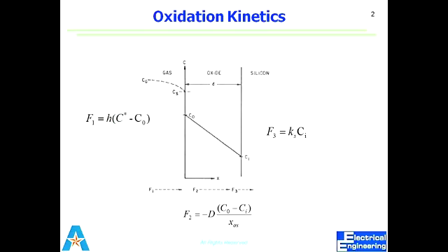She is absolutely right, that the distance matters. That's why I was saying that the thicker the layer, the harder it is for the molecule to get through, because it's getting thicker and thicker. When the oxide layer gets thicker, the rate goes lower. It's more difficult for the oxygen molecules to reach the surface of the silicon. In other words, it's the diffusion coefficient, diffusion has become more difficult. Otherwise you can say that it needs to travel more distance, so it's more difficult for the molecules to get in.